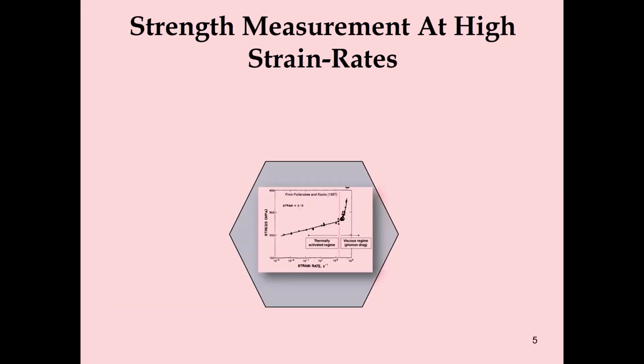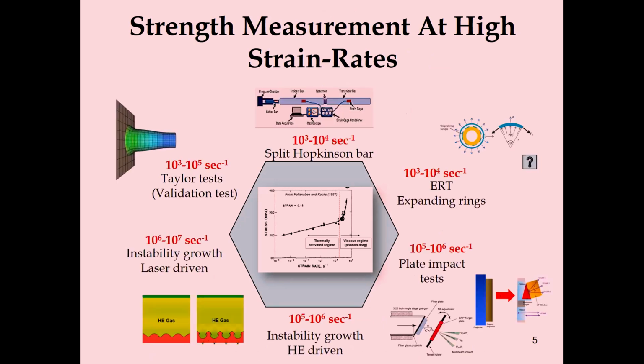So looking at this full regime of strain rates, there are, in the past few decades, several techniques for measuring strength. Of course, the split Hopkinson bar, we saw also a few works using the split Hopkinson bar yesterday. We could reach strain rates of about 10 to the 3 to 10 to the 4. And then we have the Taylor test and the expanding ring setups. And on the bottom of the slide, we could see the higher rates with the different cases of plate impact tests and instability growth, which is reaching 10 to the 6 and 10 to the 7 per second.